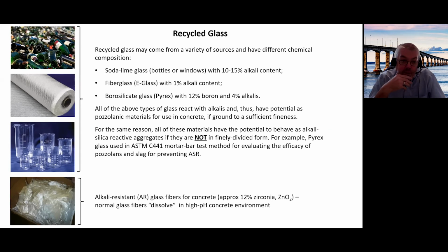Ground recycled glass is a very good pozzolanic material. Glassy materials are generally very good pozzolans. One of the problems is that the bulk of the recycled glass available is from bottles or windows, what's known as soda lime glass. This has a very high alkali content, and that raises the concern about alkali silica reactivity.